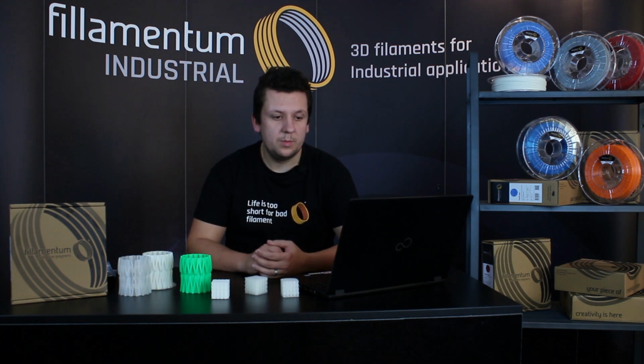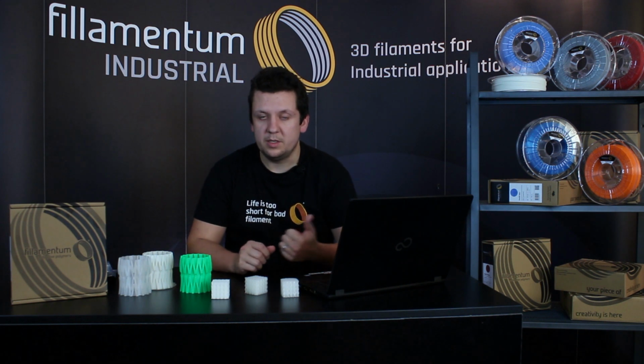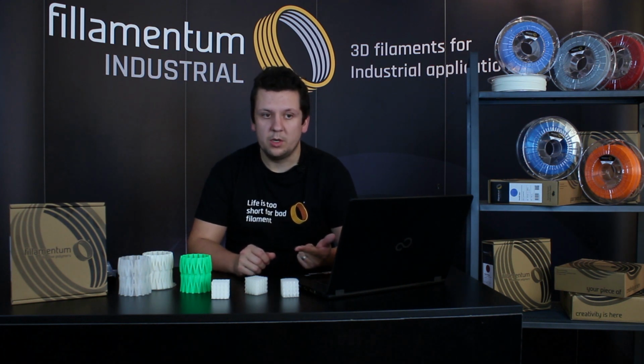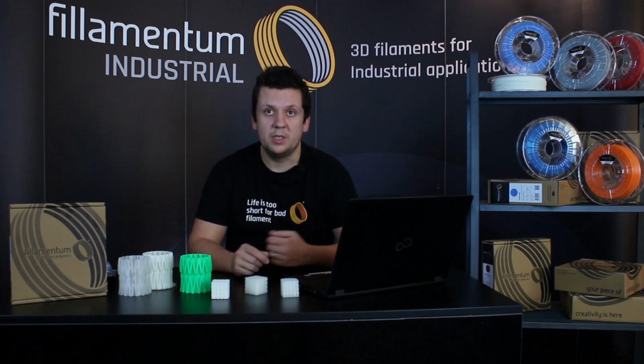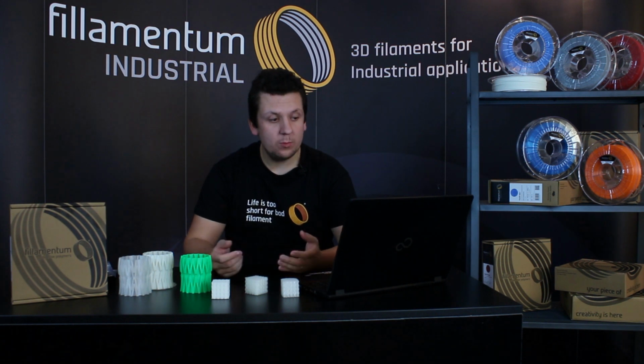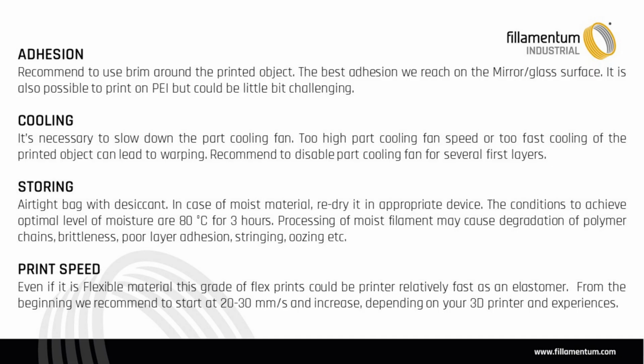So the difference between TPU and TPE is definitely in speeds, in temperature on the hotbed, the adhesion is totally different, and the printability of this material is better. Again, it is necessary to mention that this material is quite hygroscopic, so storing it in proper condition is recommended, because if you want to achieve great print results, the material must be dry. If you have a wet filament, you will see stringing, oozing, improper layer bonding, and so on.